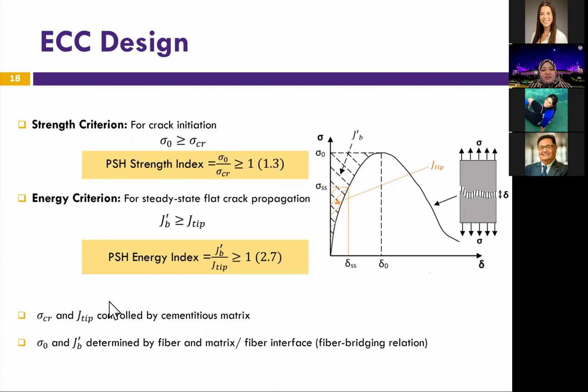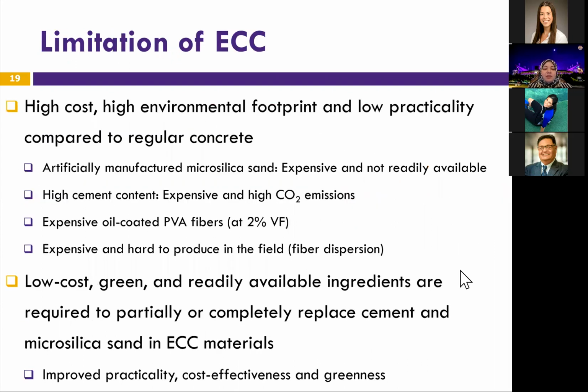The design of ECC is based on fracture mechanics principles. Sigma critical and J tip are controlled by the cementitious matrix, while sigma naught and JB are controlled by the fiber matrix interface. Both criteria have to be satisfied for us to get the pseudo-strain hardening behavior. And I'm going to talk about that more in a second.